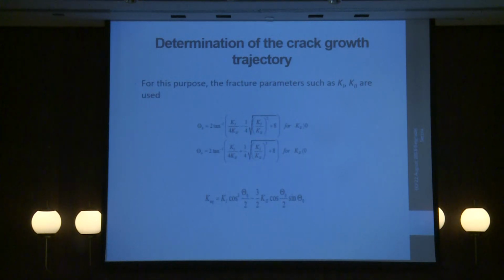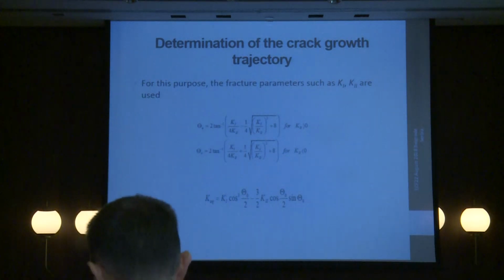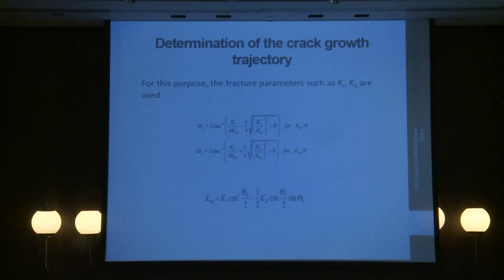For determination of the crack growth trajectory, we need to determine this angle theta, the angle for each increment of the crack length. We take the initial crack length, and then for each increment of that crack length, we find the new angle and calculate the equivalent stress intensity factor using the stress intensity factors for mode 1 and mode 2. That angle we calculate from these equations, depending on whether the stress intensity factor for the two modes is a positive or negative value.